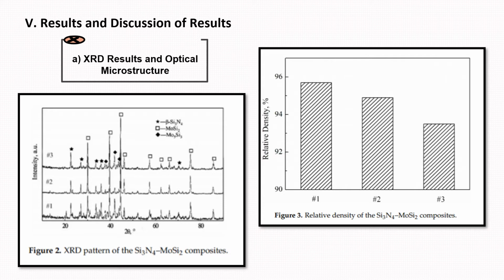First, we have the XRD results and optical microstructure. The figure on the left shows the XRD pattern of the silicon nitride molybdenum disilicide composites. The composites, after hot pressing, were mainly composed of the beta silicon nitride and molybdenum disilicide phase. Neither yttrium nor lanthanum compounds were detected.